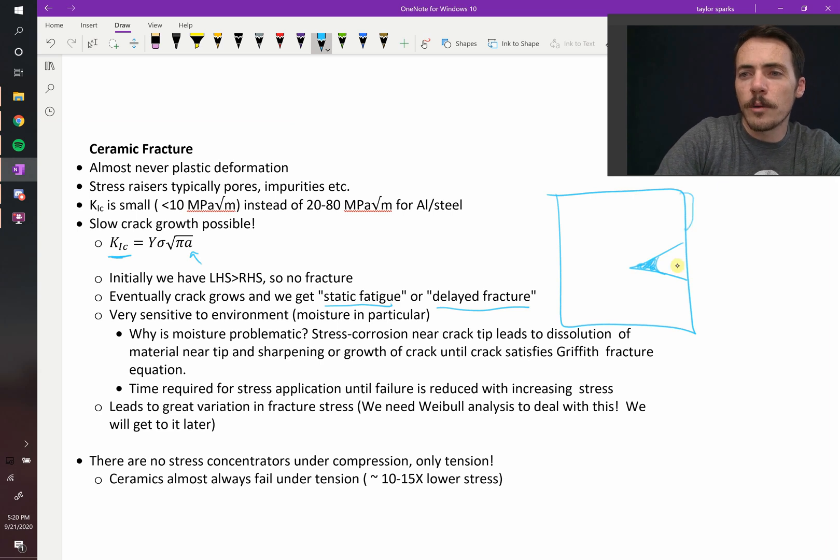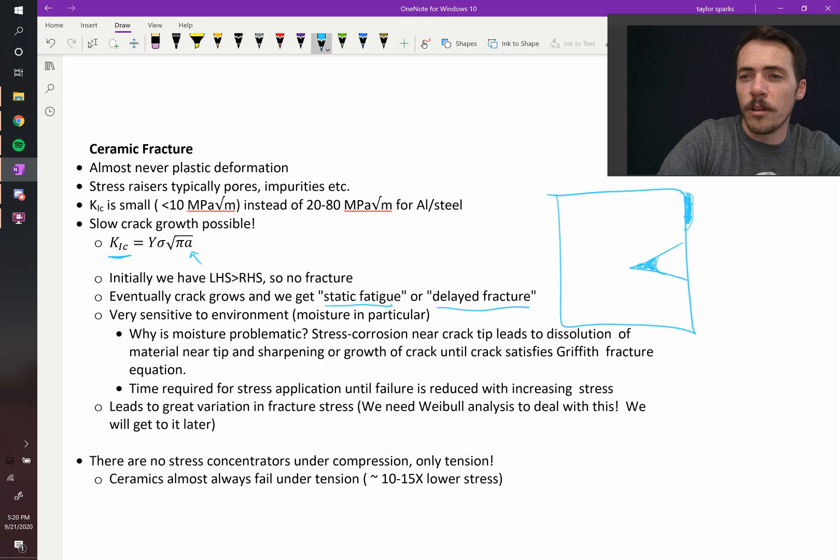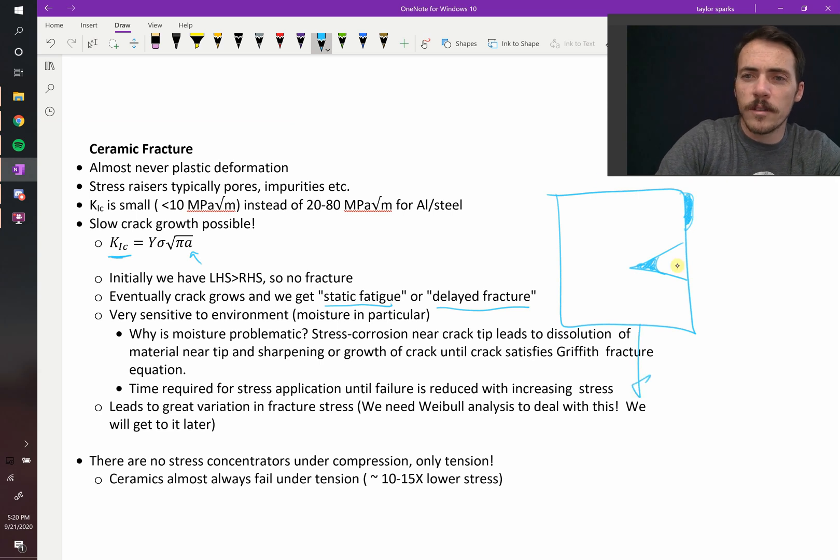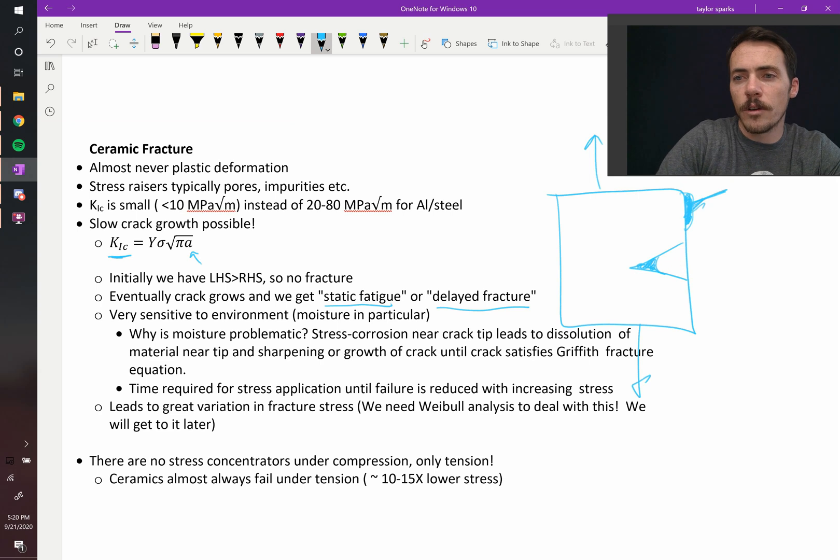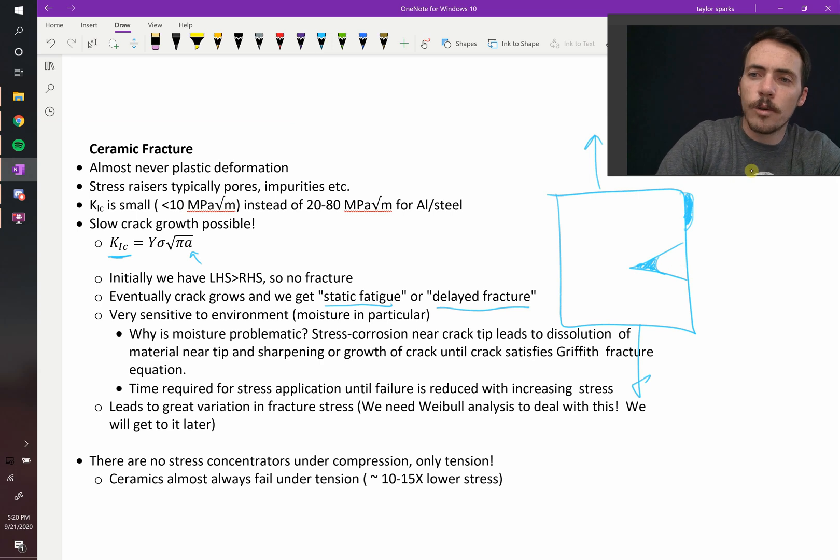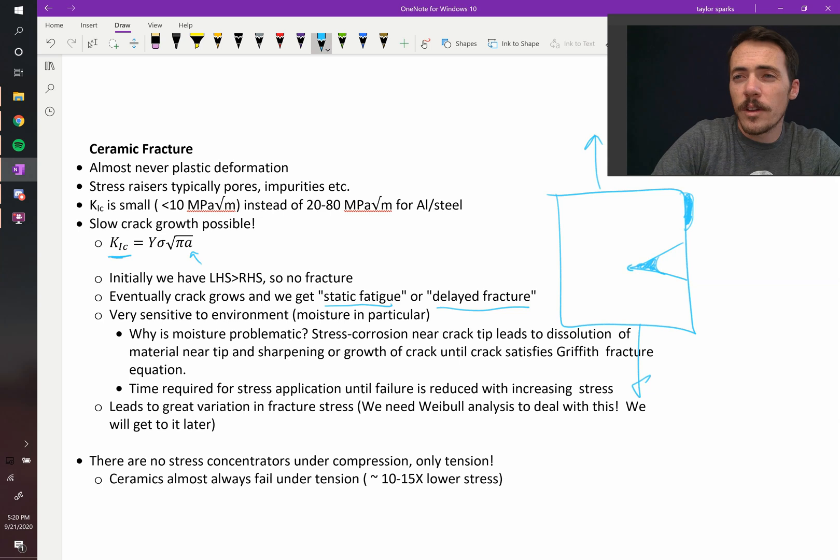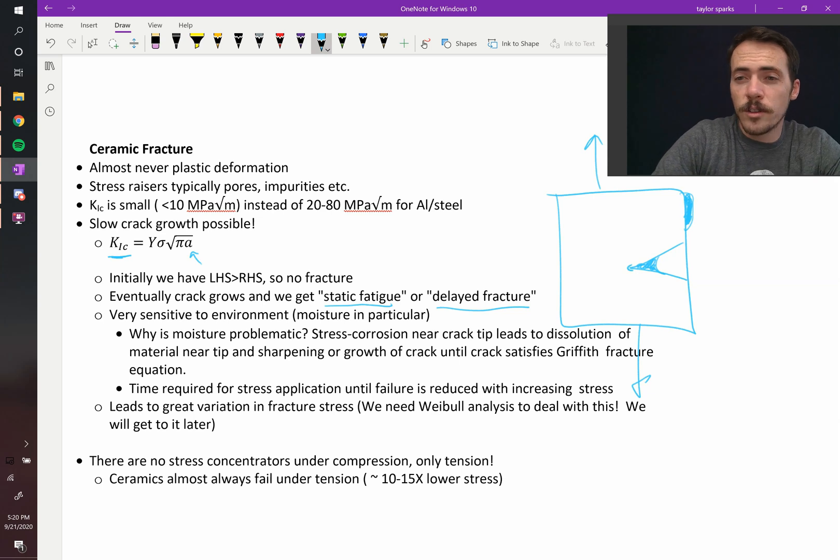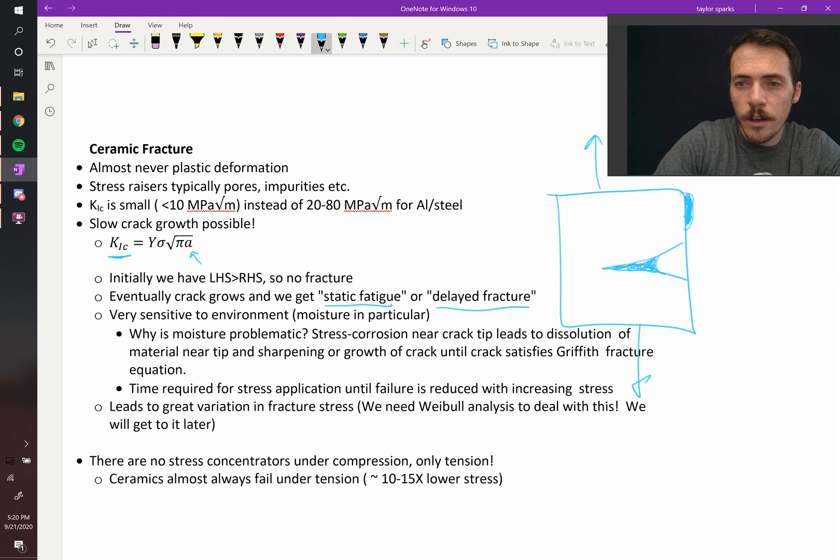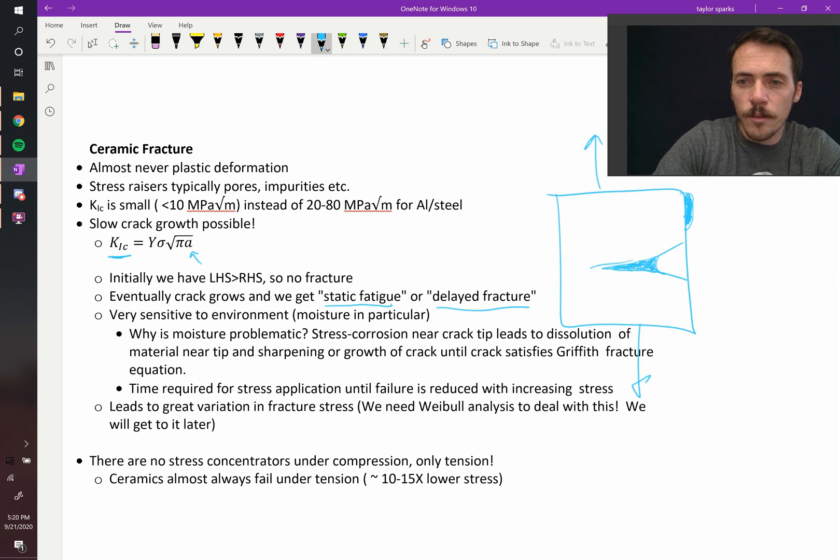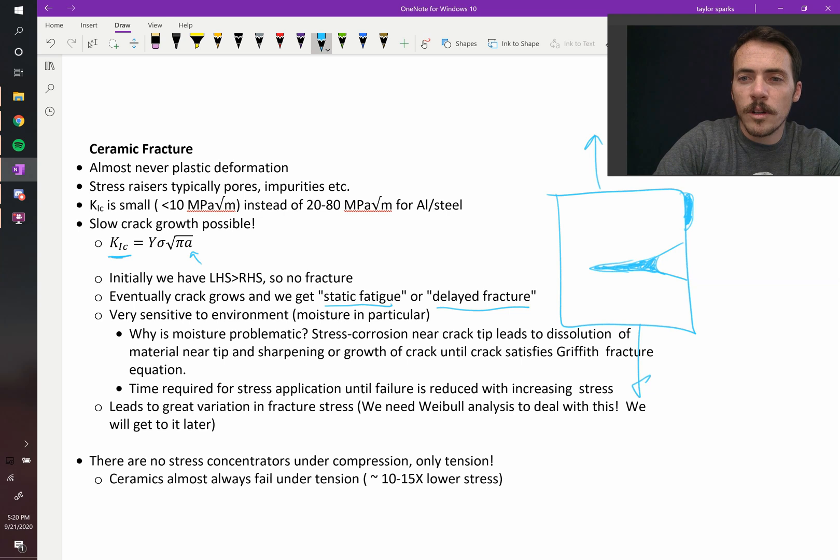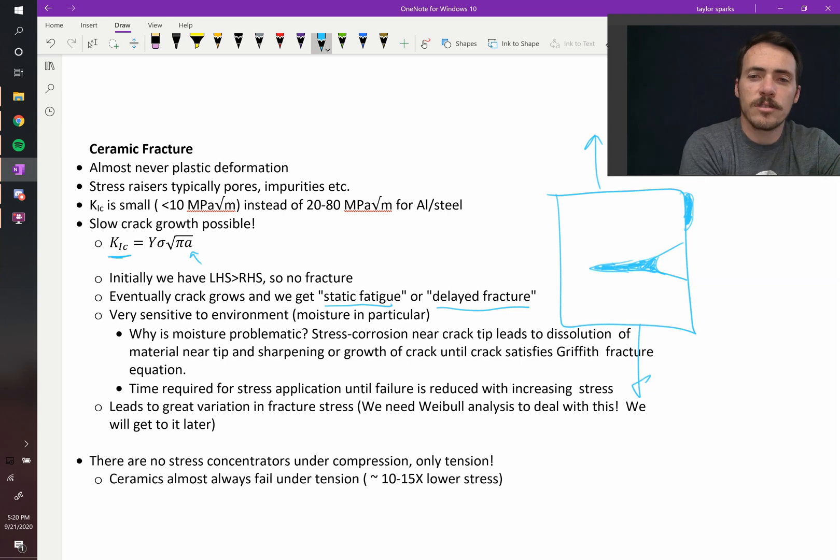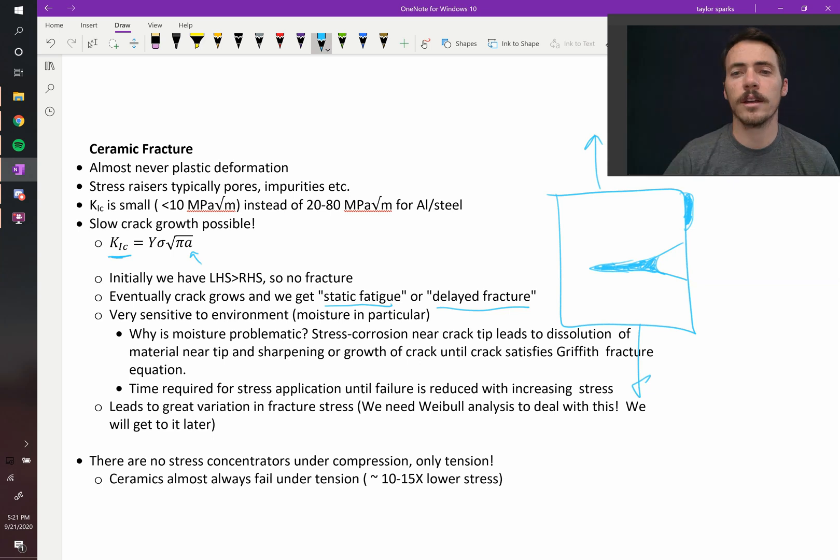Out here, if there was water, let's say that the ceramic would not be very soluble at all. It's not going to dissolve in the water. But if you're loading this thing, even though out here it's not soluble, you can get a scenario where at the tip of a very high radius of curvature crack, the ceramic does become soluble. It dissolves. And in doing so, as it dissolves, it extends the crack further. And makes it a little bit sharper, and then that extends it further, and you end up with the material dissolving away only right at the very crack tip.